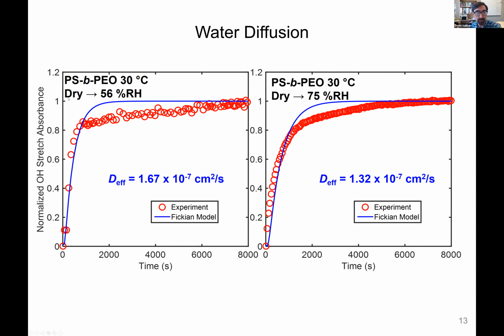And we did a number of different experiments from the dry membrane to different humidities. And then this blue curve that's being shown in these figures is the best fit of a Fickian diffusion model.